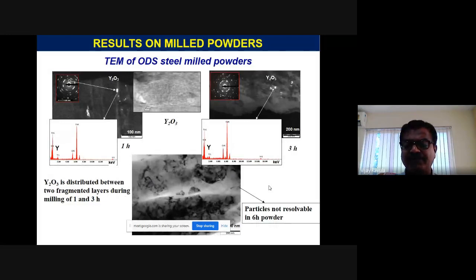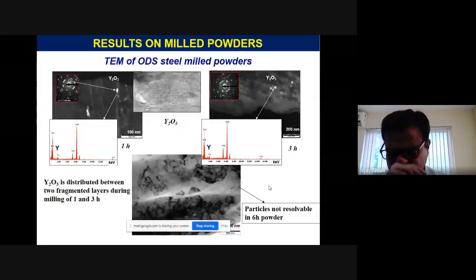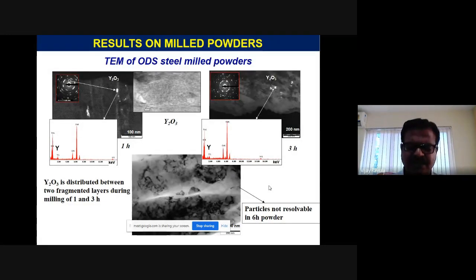And when we put that in the mill, ideally the reaction is to form this, as I mentioned to you, Y2Ti2O7 particles are to be formed. Then this yttria should dissolve in the matrix and should not be there. It should completely dissociate and then dissolve.